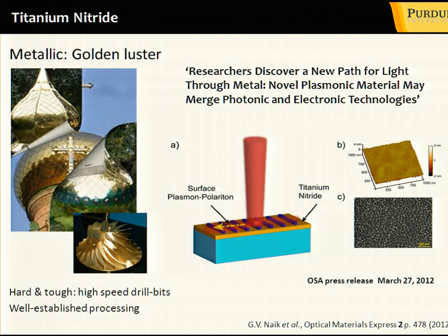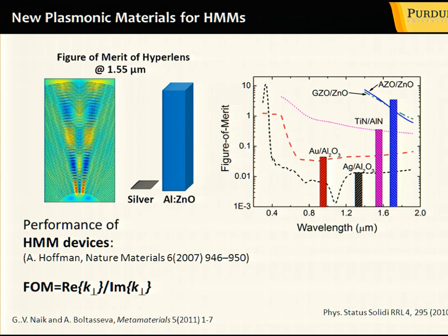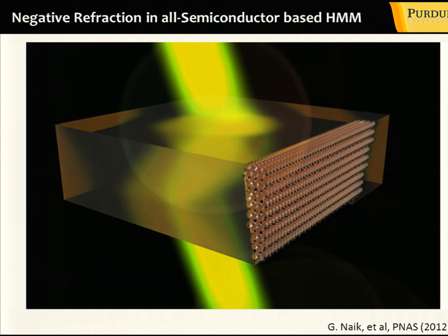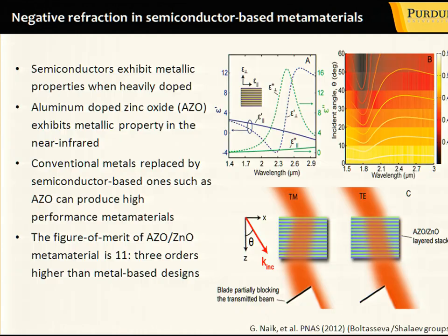And the Boltasseva group recently showed that indeed it could operate as a plasmonic material. For example, it supports surface plasmon polaritons. And you could grow it with epitaxial accuracy, so it could be extremely flat. So it is a promising plasmonic material for the visible part of the spectrum, at least for some applications, such as very important hyperbolic metamaterials, which I will speak about a bit more later. They actually showed that these transparent conducting oxides and titanium nitride outperform traditional plasmonic materials by several orders of magnitude. And just to illustrate that these materials could indeed work as metamaterials, we showed negative refraction in these materials.